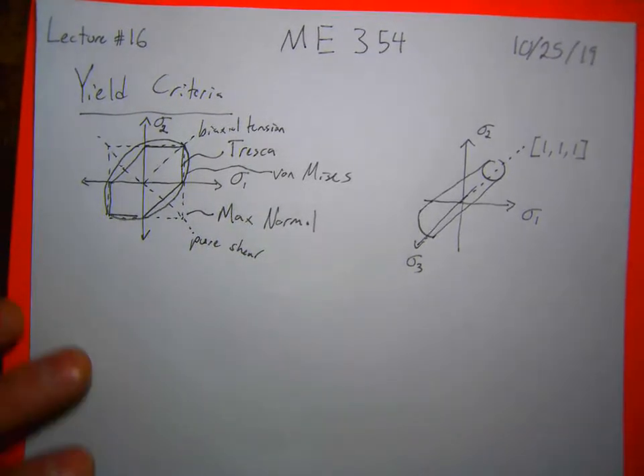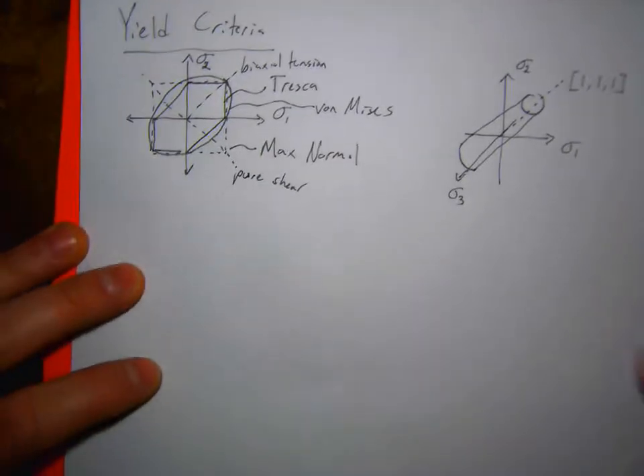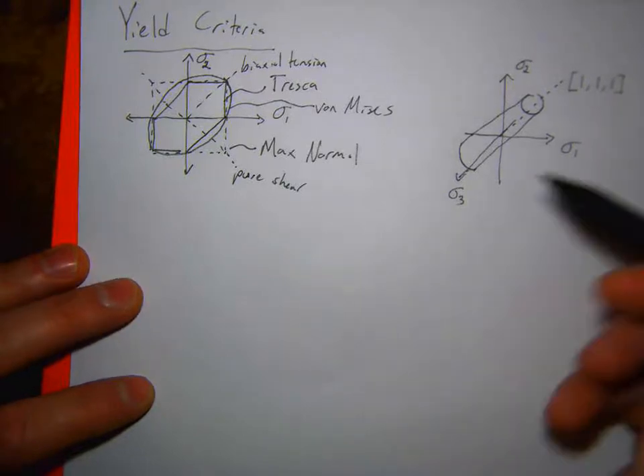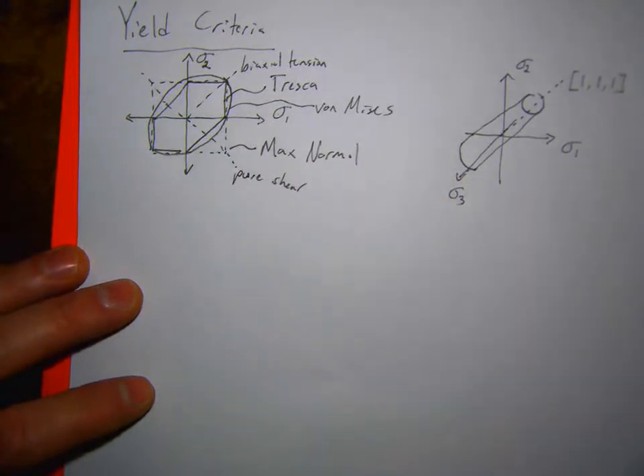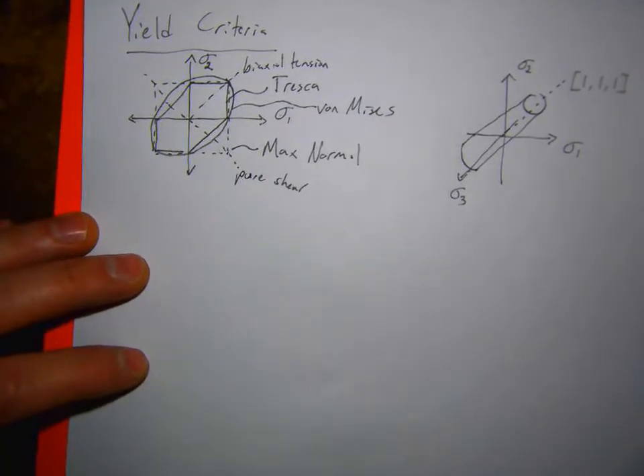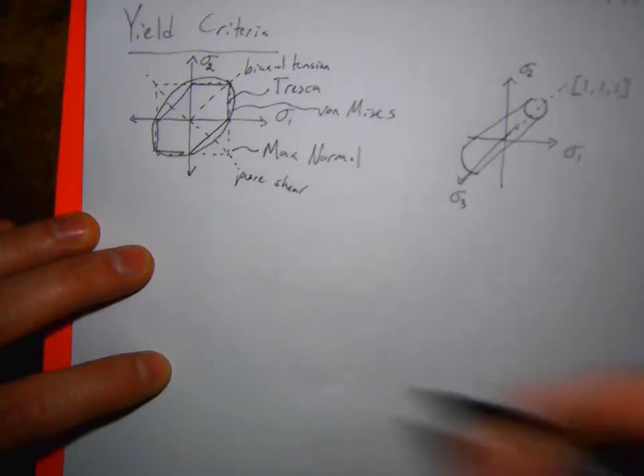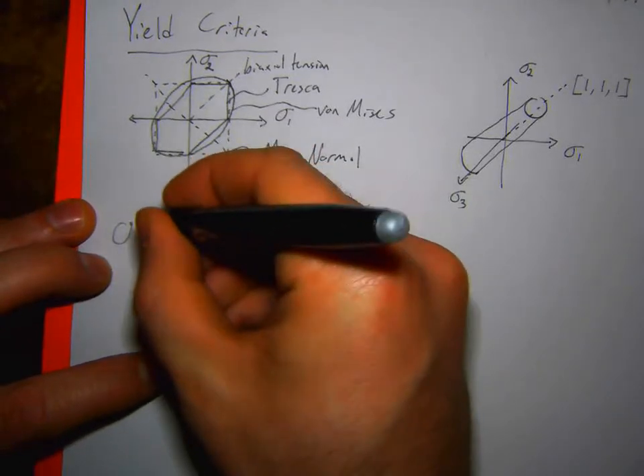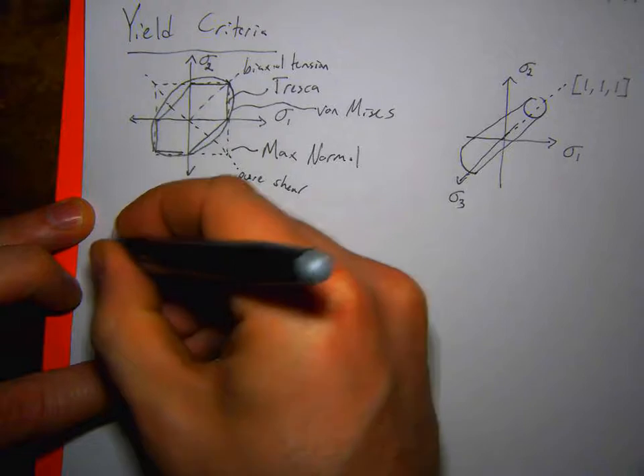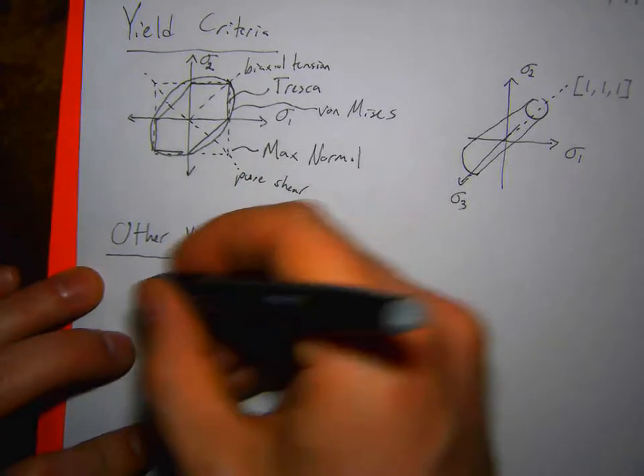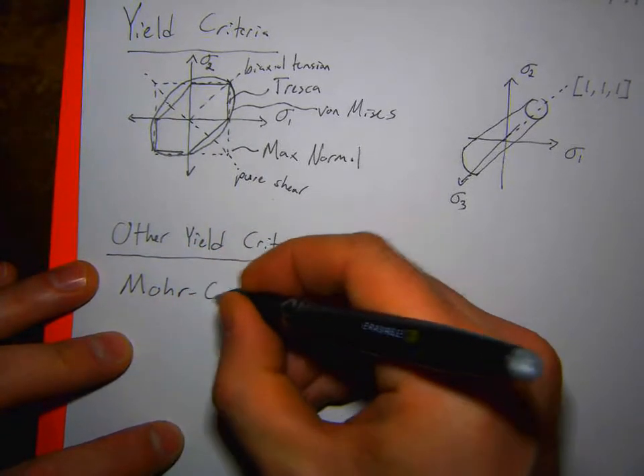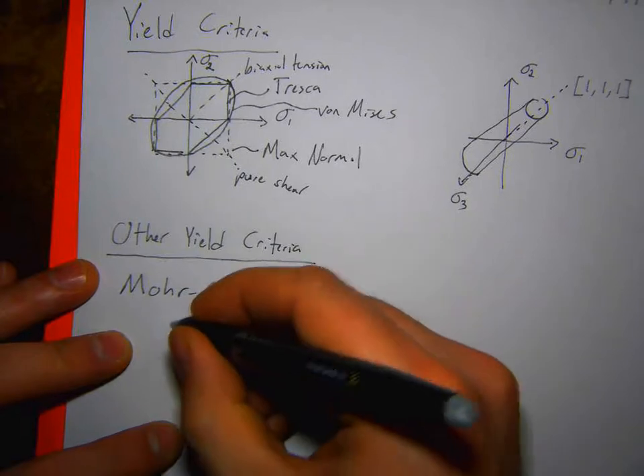If we have anisotropic materials or pressure-dependent materials, there are some other useful common yield criteria that pop up. One of them is called the Mohr-Coulomb. The max normal stress criteria is normally used for brittle materials because they generally fail in tension or compression. The compressive yield strength is a lot higher than the tensile yield strength because in tension, cracks and voids cause failure to happen a lot earlier — which we'll talk about in fracture.